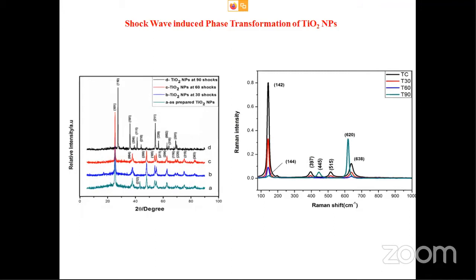Interestingly, the control was initially in the anatase phase. After giving 90 shocks, the phase is completely transformed to the rutile phase. See, this is the rutile phase. This peak is completely newly generated; it's missing in the anatase phase. This peak corresponds to the rutile phase. So shock waves can change the phase of nanomaterials, even. It is working with the crystals also.